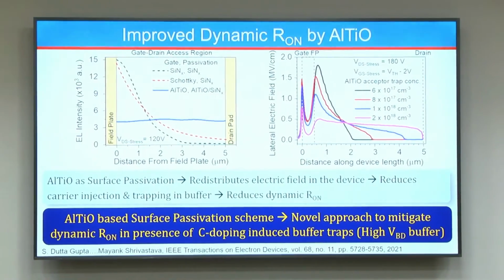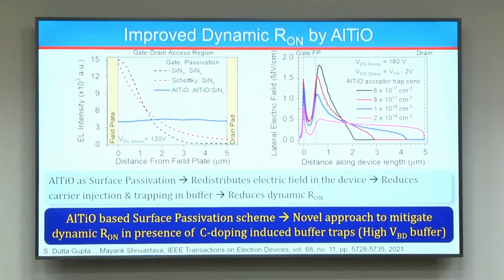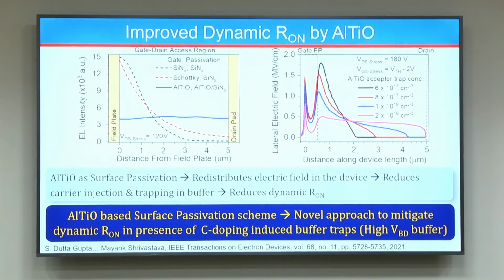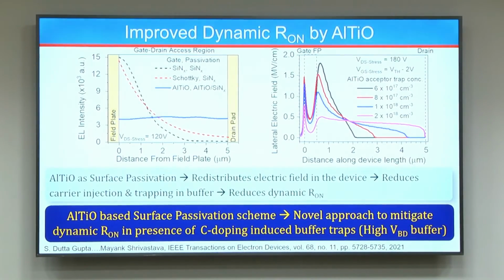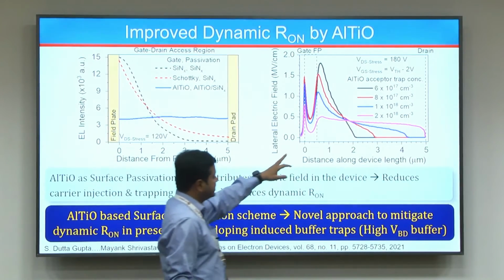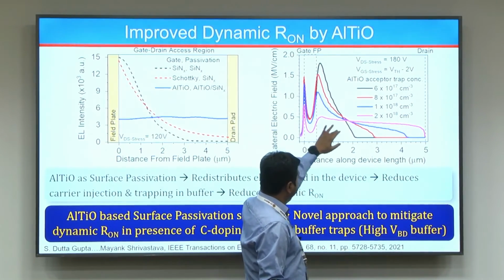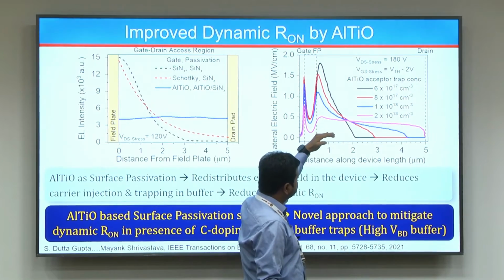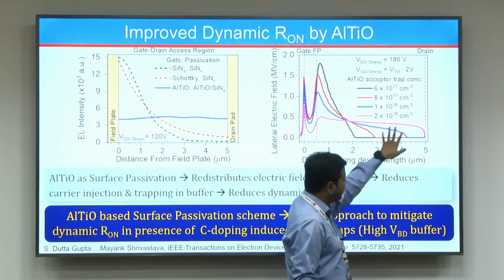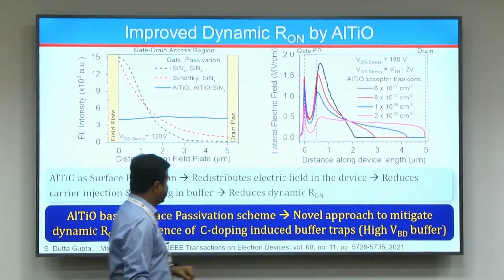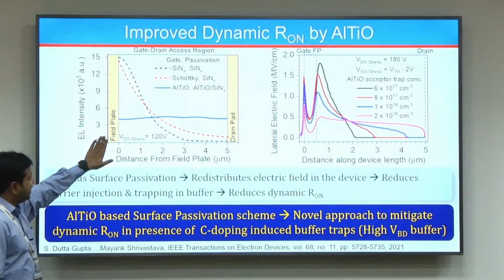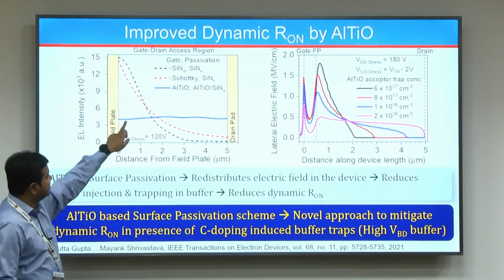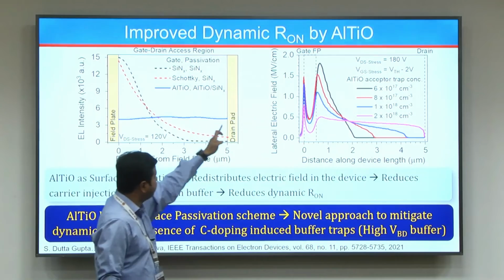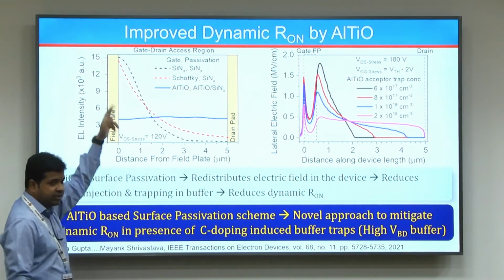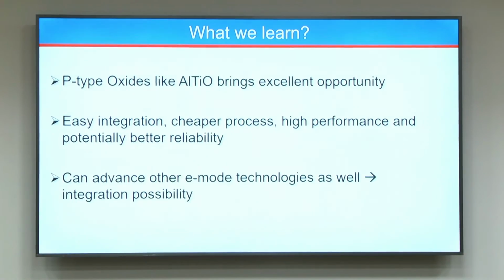So we published another paper on that, the details are there, but what we found is that the AlTiO, because of the p-doping, also helps distribute the field, and depending on the amount of acceptor trap concentration, you get a different kind of distribution, and as you go higher, the field spreads all across the access region. So this is confirmed by the EL intensity graph here, where you see that in the case when there is AlTiO, the field is all uniform across the access region, unlike the other cases where the field is peaking at the gate side. So this is what we did.